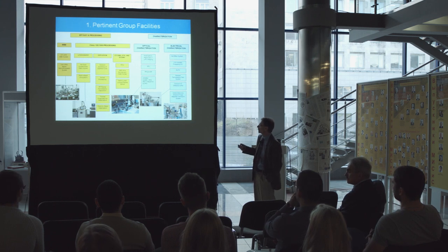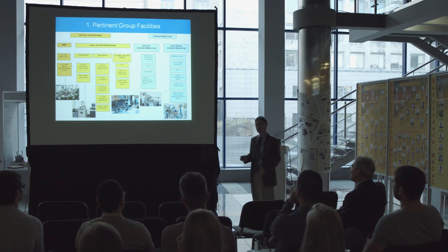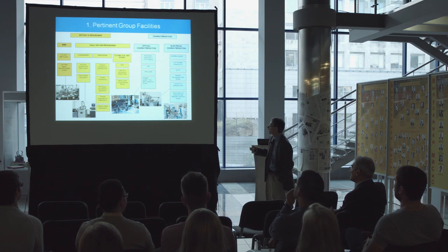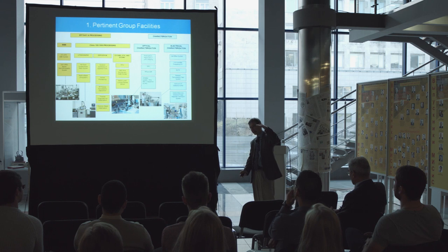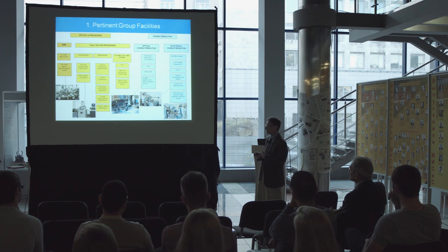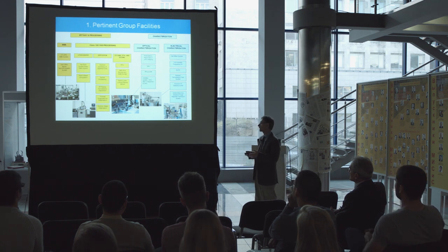In conjunction with these, there's all sorts of processing, like dry processing, which means that you pattern something and then you can dig down and create three-dimensional nanostructures from the same approach. With that, we have characterization facilities. Just like in normal material science, you think about growth, property, characterization. So we can look at these complex nanostructures with techniques such as ultra-fast optical spectroscopy. That means you pump light into the structure, and the high energy radiation, as it decays down through the energy level structures, gives you back radiation, which we can look at in time and in wavelength, giving us both the energetic spectra and the dynamics of the movement of the energy as it dissipates through the system.